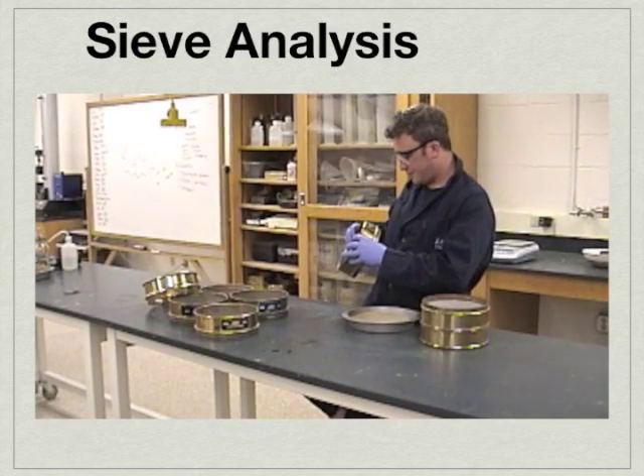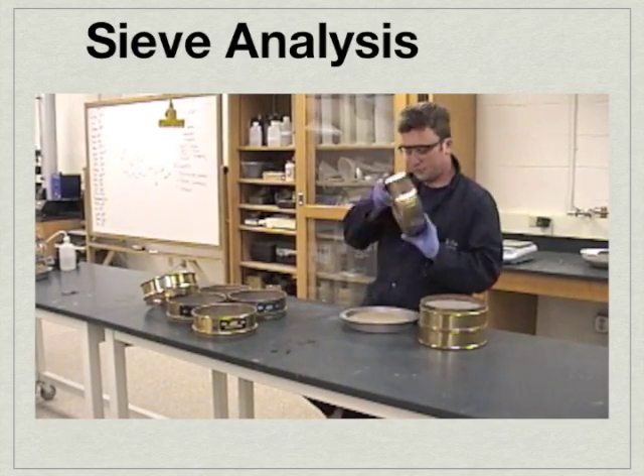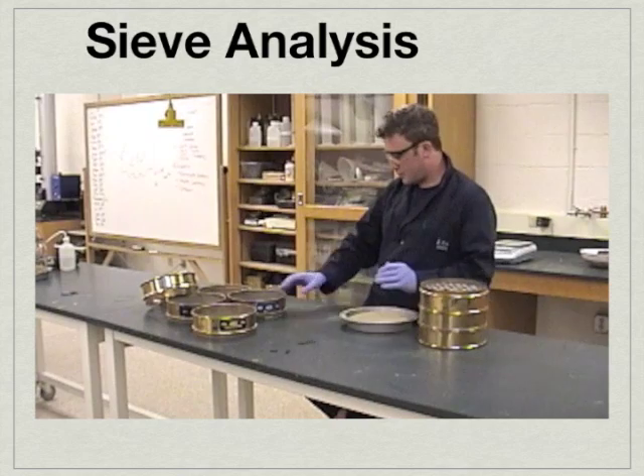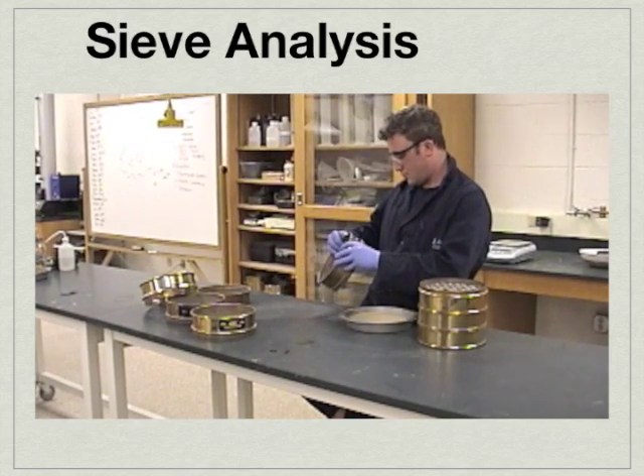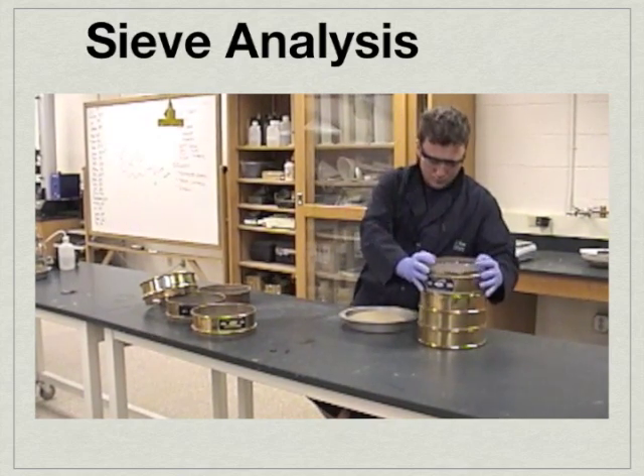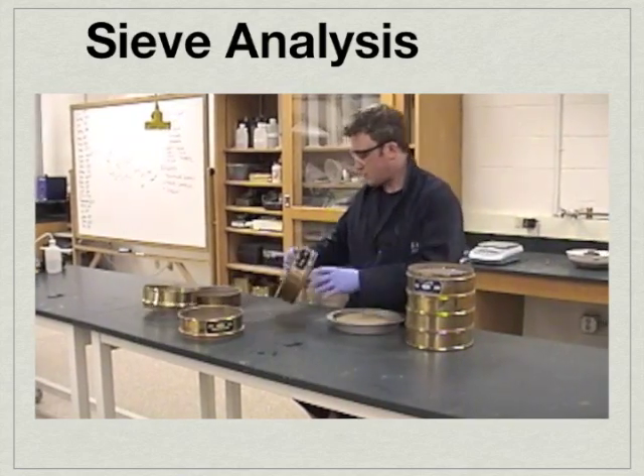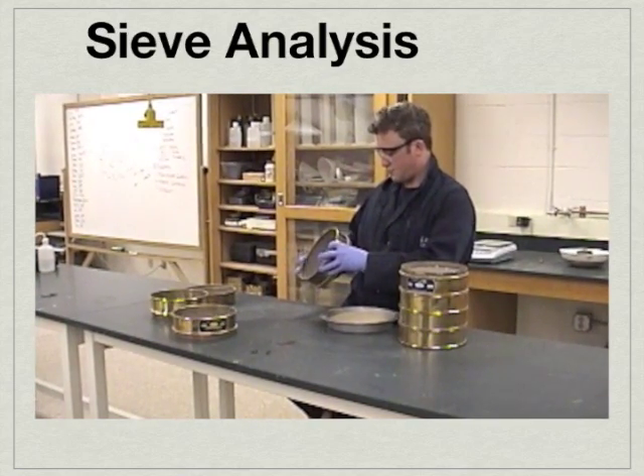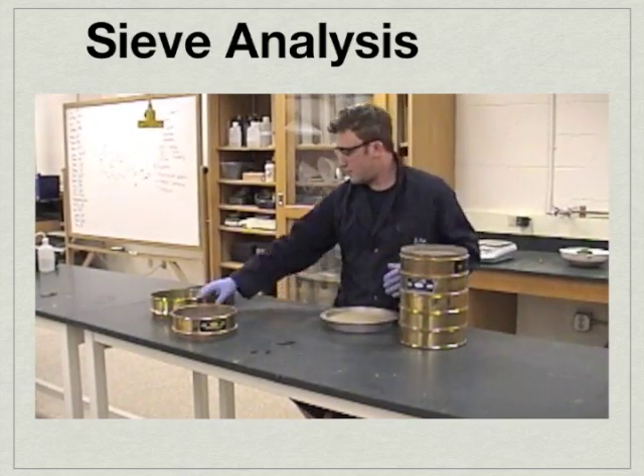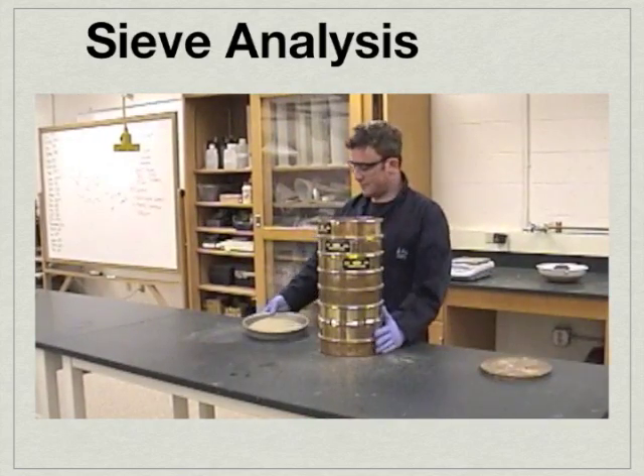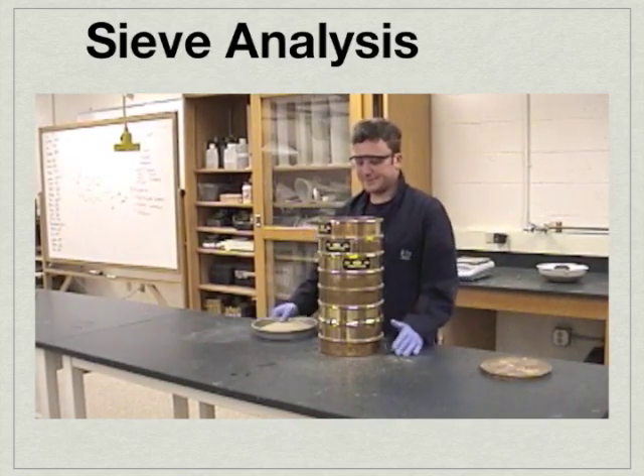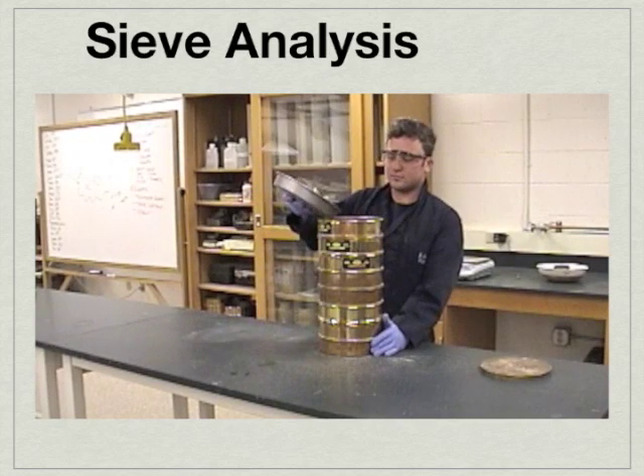So let's go ahead and do an example of a sieve analysis. Whenever we do a sieve analysis, we start with the coarser sieves and move down to the finer sieves. Here we're going to be doing a sand analysis, so we'll start with the 3/8 inch sieve, move to the 4, 8, 16, 30, 50, 100, and then the pan.